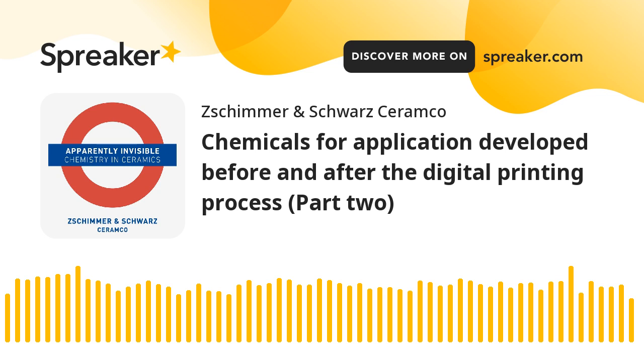Another action that can be taken to avoid the accumulation of water vapor is to increase the density of the engobe or of the glaze by using a different kind of chemicals, so to drastically reduce the water amount during the application. I know it's quite obvious and maybe ridiculous, but the water reduction, of course, stands for a vapor reduction. Anyway, the target is to develop the proper conditions in terms of fluidization and rheological stability in order to work with higher density values without affecting the good leveling of the engobes or of the glazes.